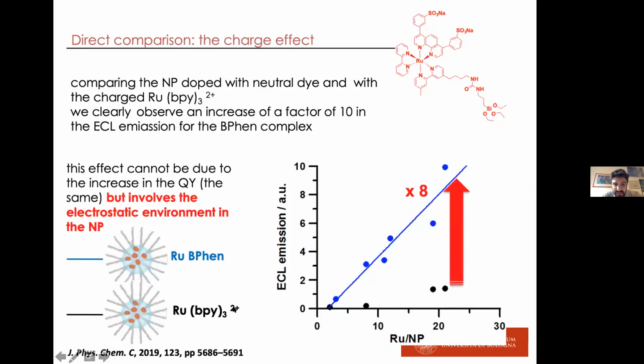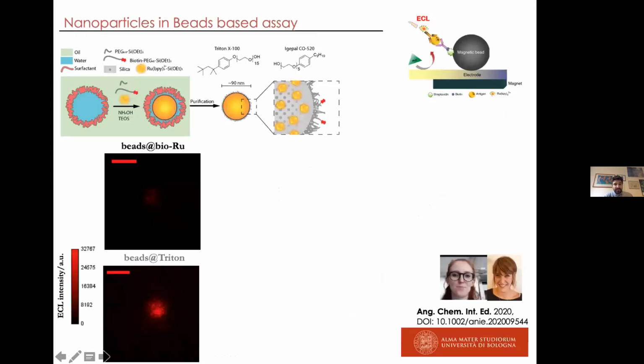And by comparing the two dye-doped nanoparticles, with the ruthenium bathophenanthroline neutral dye or with the ruthenium tris-bipyridine, we have this increase, because in one case, the ruthenium tris-bipyridine, there is a plateau due to the zeta potential, while in the case of the neutral dye, we can have a linear trend. And this brings me to my last slides, I think,